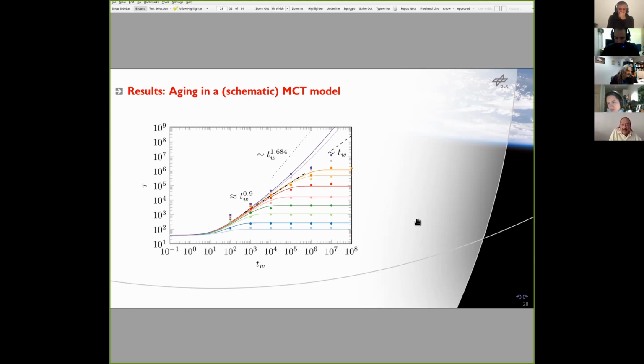And what I did here is something that we like to do within MCT. We have the asymptotic solutions, but to get a little bit more than just the asymptotics, also some pre-asymptotic corrections, etc., you can build a schematic model that you tune to have the same power law exponents as the full model that you want to solve. And that's what I did here. I replaced the purely asymptotic solution with a simple-minded schematic model of MCT. But I do show also the scaling predictions, which are the dashed and the dotted lines here.